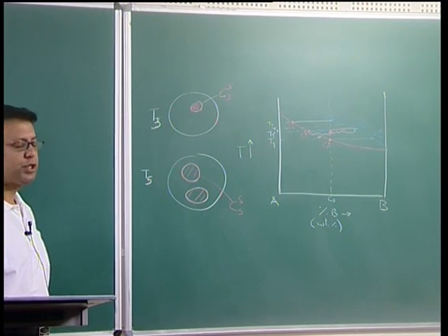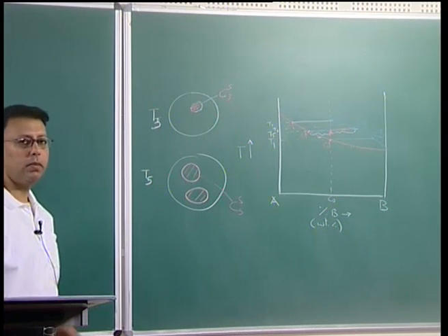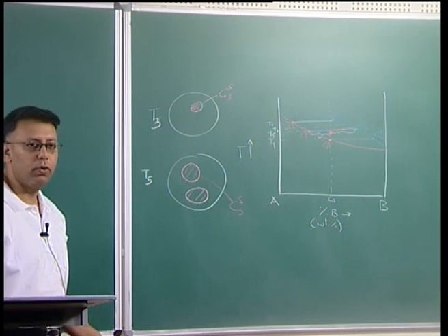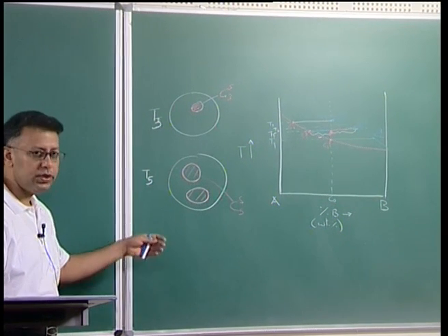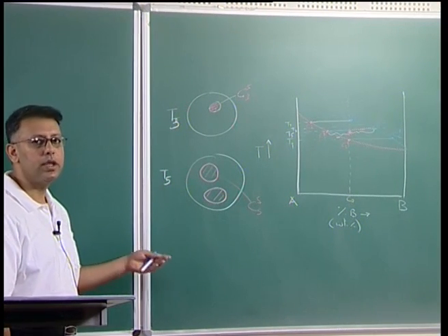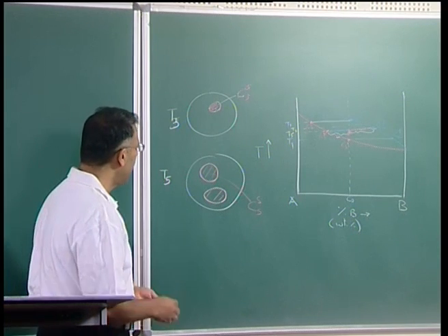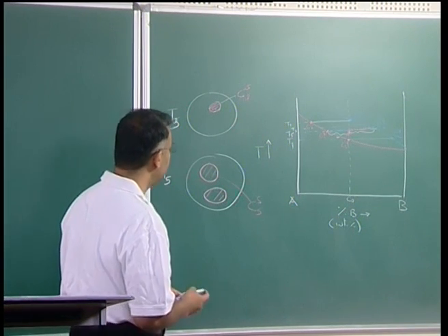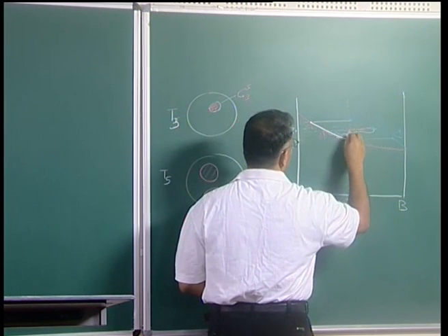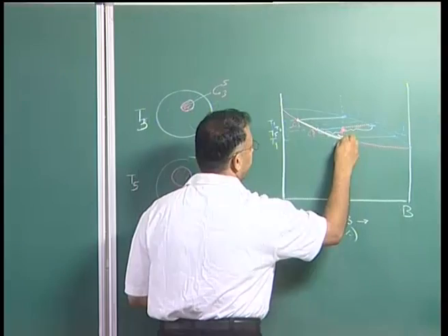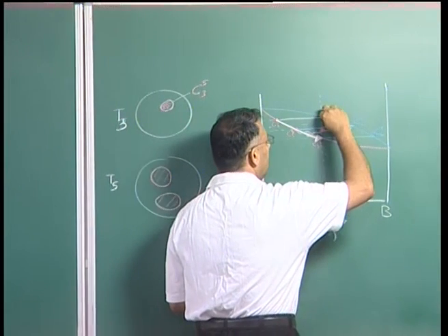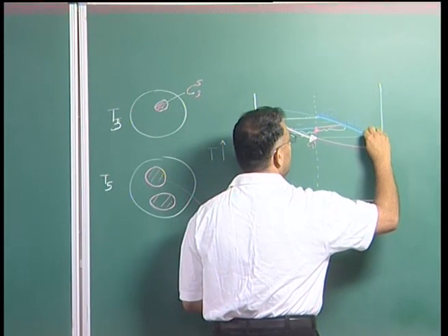That means, if equilibrium has to be maintained, this original solid which formed has to diffuse in it more of B, so that it becomes richer in B, and therefore, the composition is constantly changing to maintain what we call equilibrium, that means to be in accordance with the phase diagram. Now, therefore, I note that my composition of the solid is changing along this line, the bottom part of the curve, and the composition of the liquid is changing along this line, which is the top part of the curve.